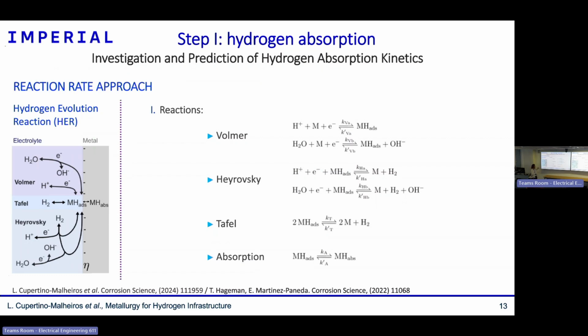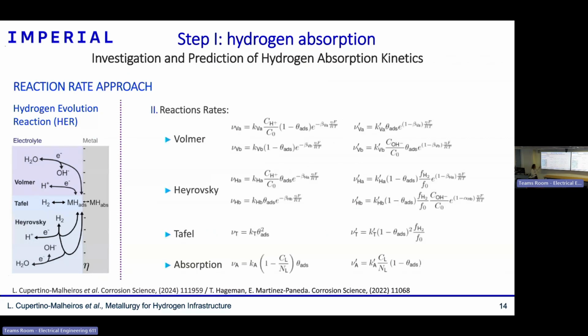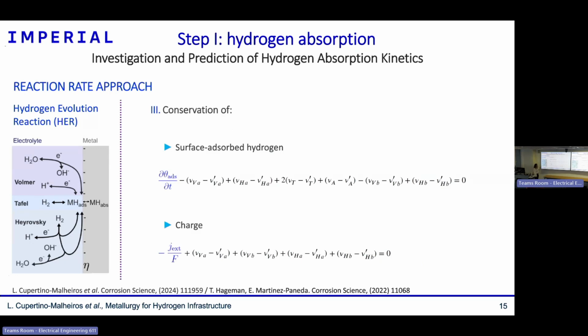So once identifying those reactions, I then take the reaction rates of all those reactions, which come with some kinetic constants that I'm interested to know, to be able to predict the hydrogen production and absorption. And finally, by just doing conservation of the adsorbed hydrogen and the charge, we can get a model. But of course, this model needs some kinetic constants, and therefore I went to the lab to do some